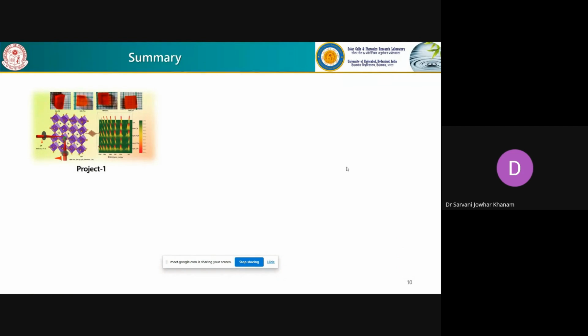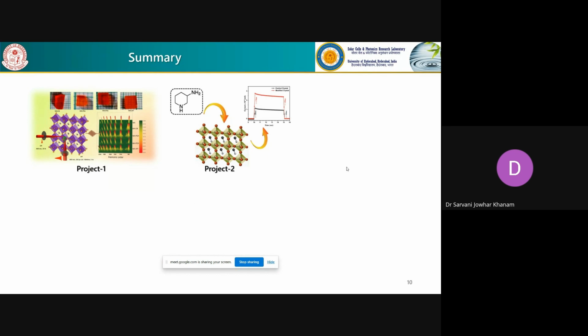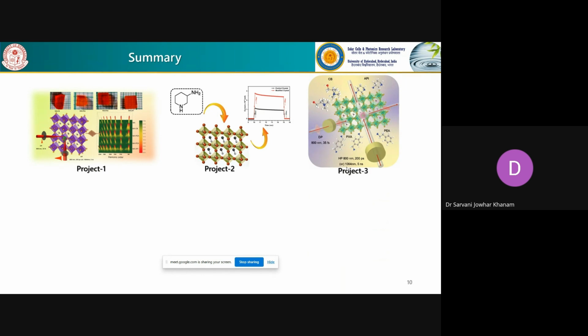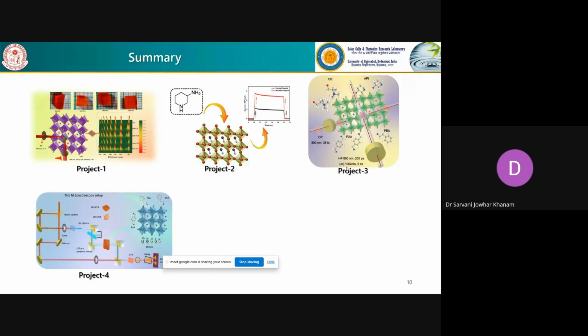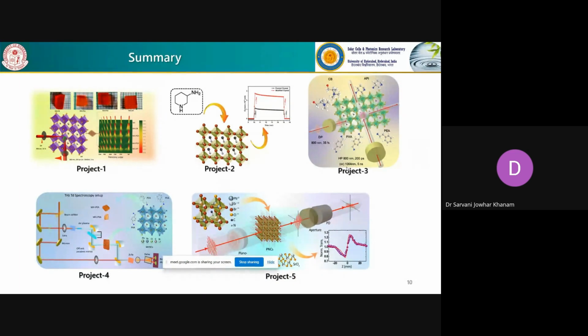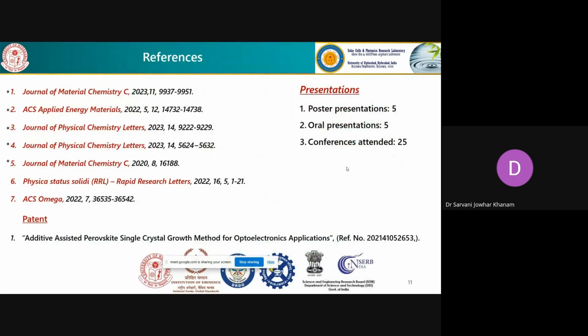In summary, in the first project, we have successfully optimized the conditions of the additive engineering method, and in the second, we did the same for optoelectronic applications, like IV studies. In the third, we checked whether this technique works for mixed halides or not. In the next project, we used these single crystals for transmission studies using the terahertz spectroscopic setup, where we concluded that the defects are lower in modified single crystals than in the pristine one. And in the last project, this is on perovskite nanocrystals for non-linear optical studies. These are the references.